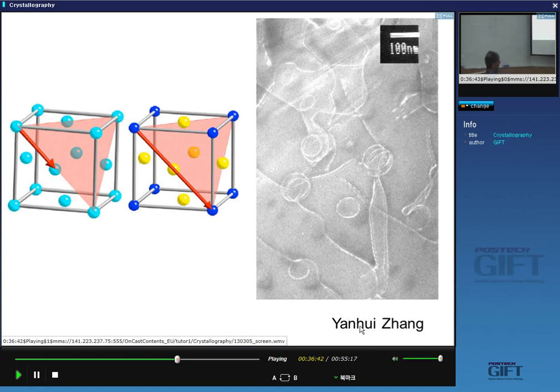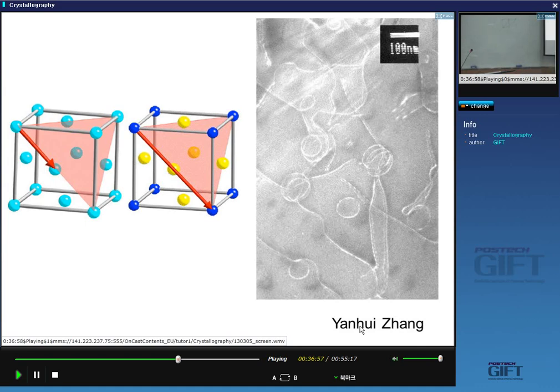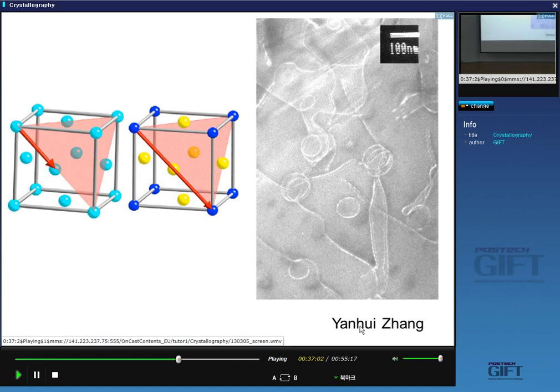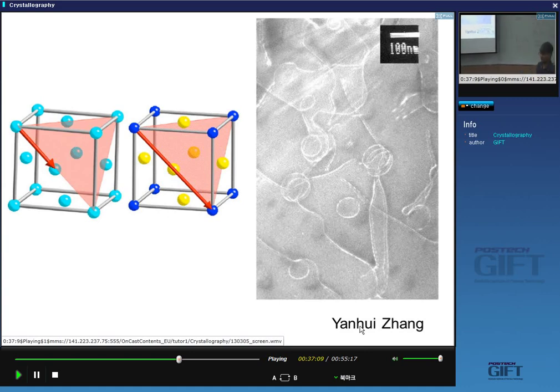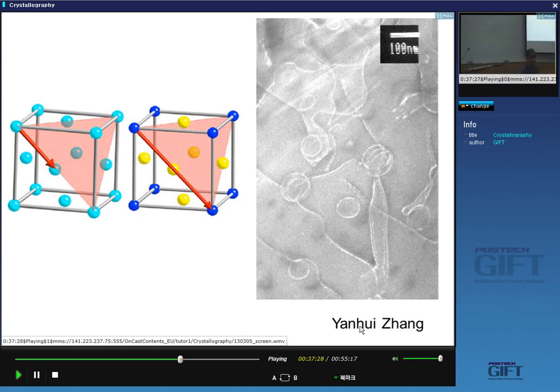In transmission electron microscopy you can see dislocation pairs — not a single dislocation but a pair. To enter gamma prime, two dislocations on the right slip plane with the right orientation must move together, making deformation difficult. An assignment question: can we create something analogous for steel — finding a precipitate coherent with the matrix and with almost the same lattice parameter?